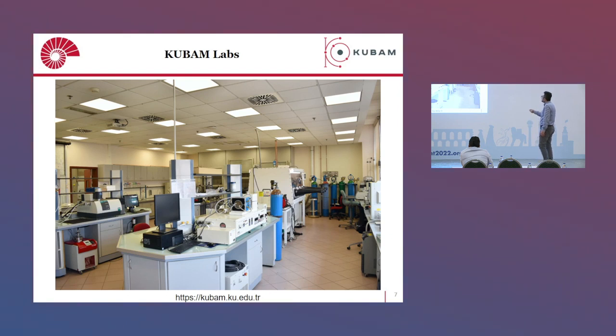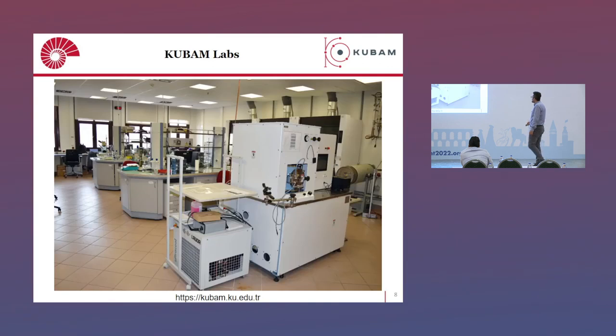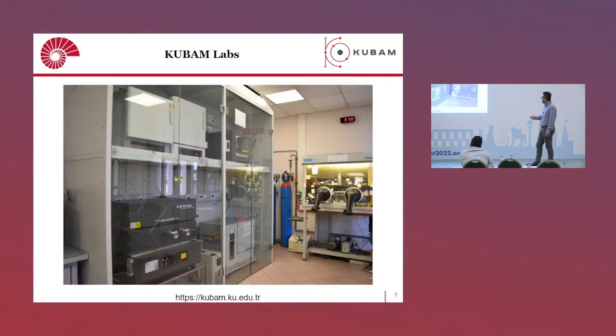Just to show you our infrastructure, this is one of our labs with a laser flash apparatus here, ZEM3, resistivity measurement, thermal conductivity measurements, our XRD, thermal analysis with DSC, TG. We have a glove box for air-sensitive materials. We have our own SPS to sinter powder materials, high temperature furnaces that we can heat up above 1500 C, and some other furnaces in which we grow single crystals, for example, by the vapor transport method.